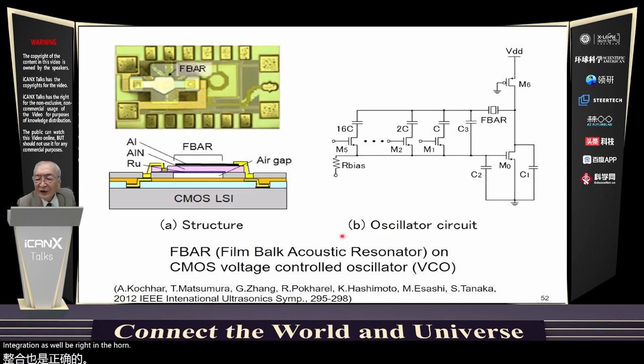Film bulk acoustic resonator, FBAR, is widely used for wireless communication. This has piezoelectric thin film made of aluminum nitride, which has electrode on both sides of the film and air gap under the film. We fabricated the FBAR on CMOS LSI for voltage controlled oscillator VCO, as shown in the slide.